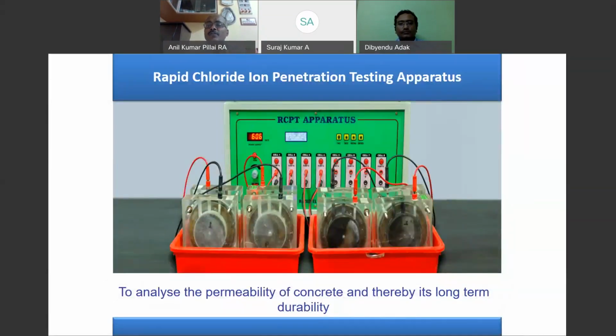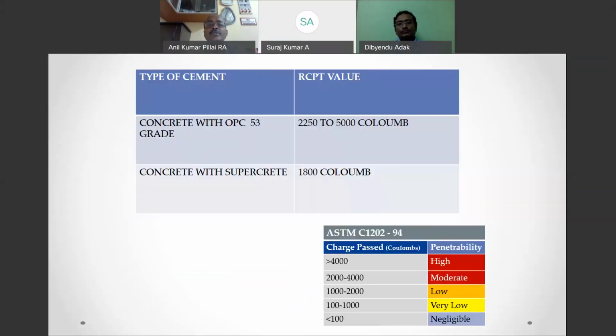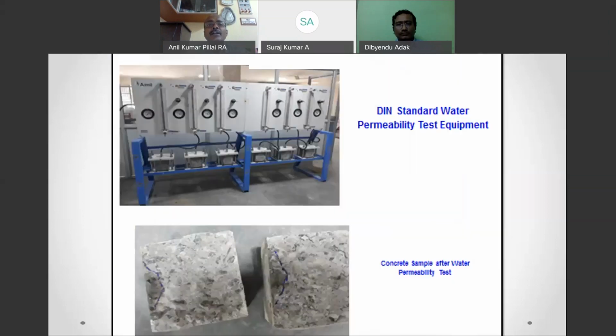Of course, we give a lot of emphasis on durability of concrete, for which we have various instruments for checking the permeability of concrete, the rapid chloride penetration test, where the concrete specimen is kept, and based on the amount of charge that is passed, you get an idea of the durability of concrete. We have also got the DIN standard water permeability test for checking the durability of concrete. Again, instead of rapid chloride, we have the water permeability that is also there.